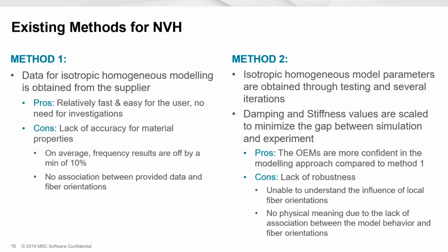So although the 10% may be good for many applications, for frequencies, we generally manage to be very accurate within 1 or 2% error. Explorations are off since damping is very highly frequency dependent and related to fiber orientation distribution.